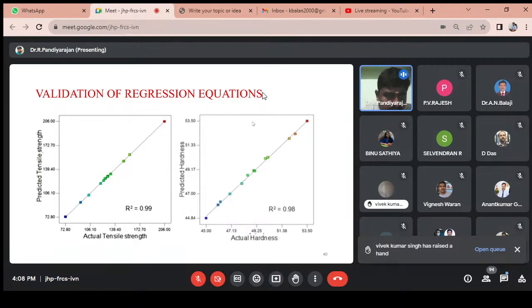If the error percentage between both is very small, we take the mathematical equation; the mathematical equation is okay. The r squared value is reflected by the error percentage of the mathematical equation. If the r squared value is more than 0.95, you take the optimum solution of the process parameter in the linear regression equation. If less than 0.90, you don't take the equation. We have to change the model and design matrix, and once again develop the mathematical equation.